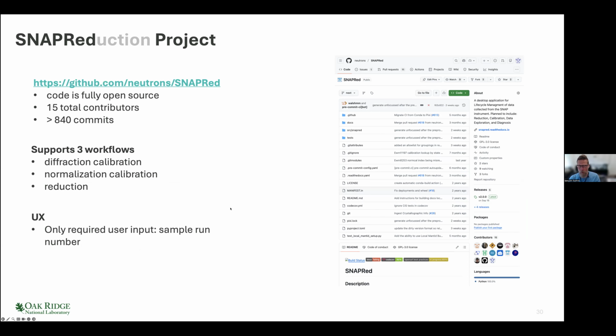A little bit more about what we made. The entire code is open source and on GitHub. You can go to this web address and look at everything. We had 15 total contributors to the code base and 840 commits. And essentially the 3 things it does is diffraction calibration, which is the conversion of time of flight to d-spacing, the normalization calibration, which is correcting the wavelength response of the instrument, and reduction of data using those 2 things.